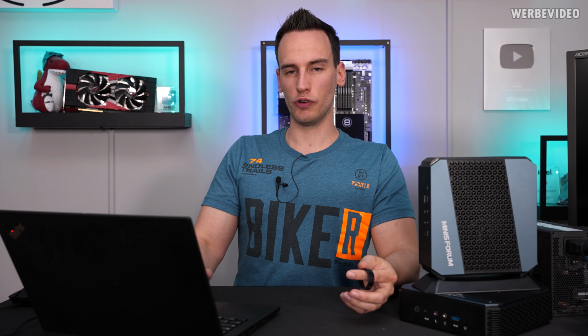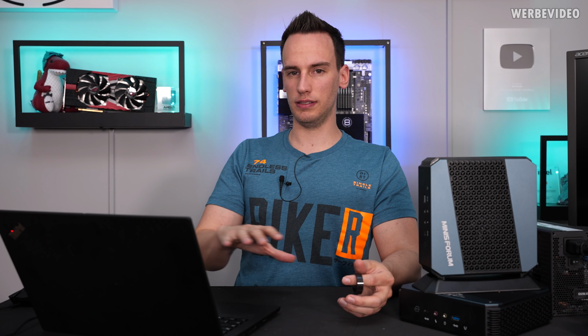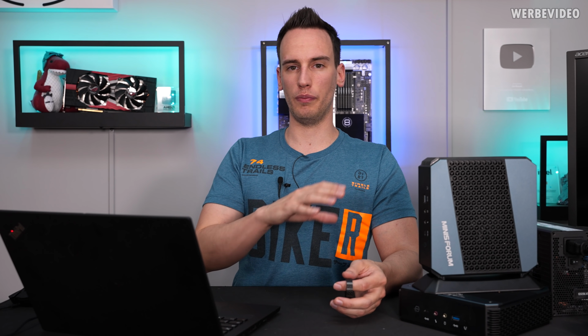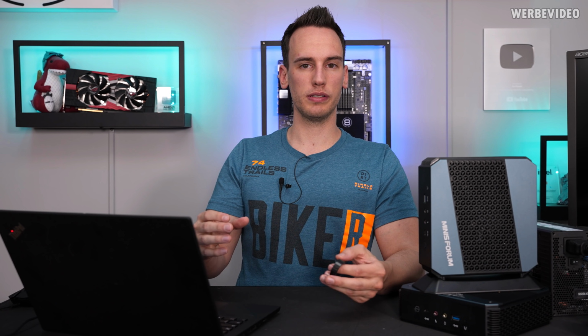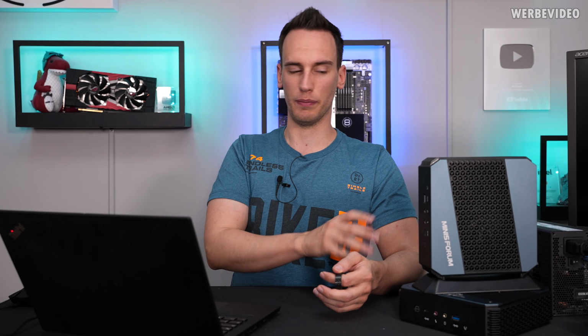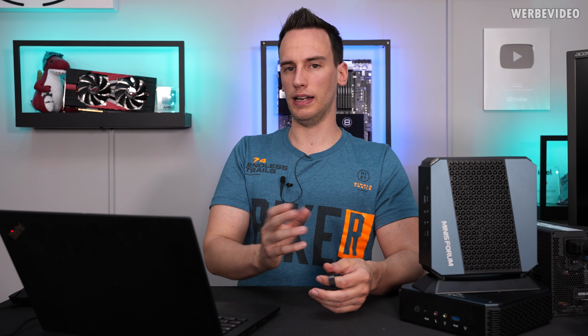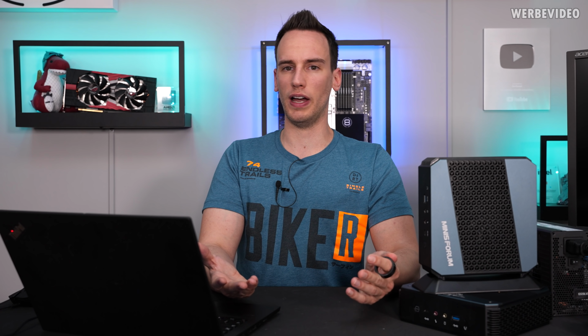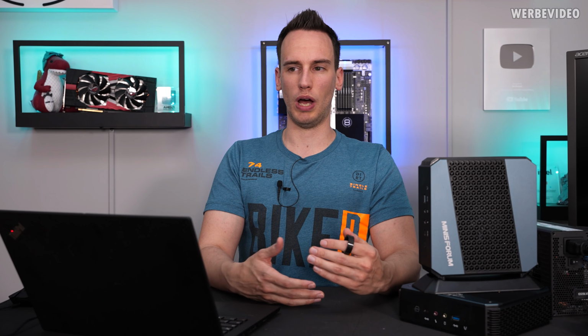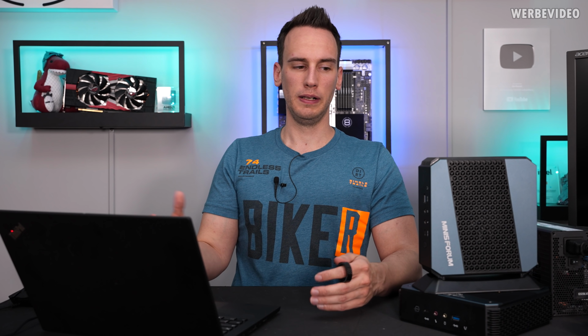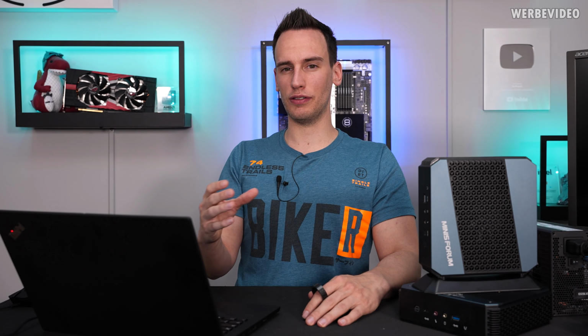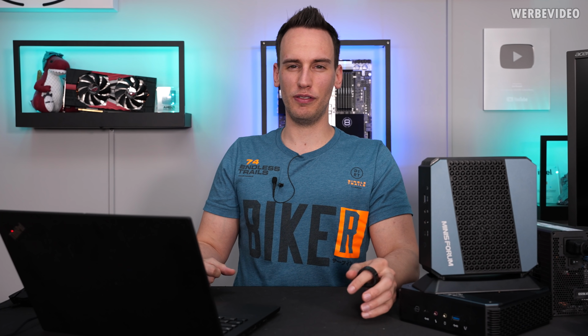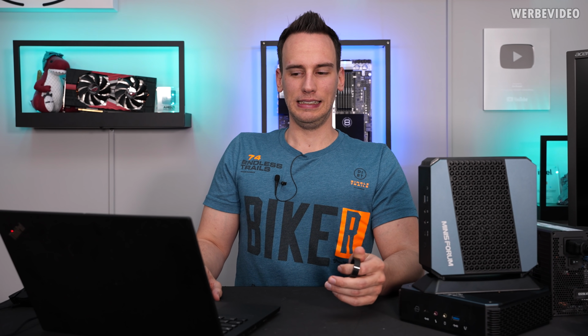3% carbon fiber. For sure, 3% carbon fiber will still impact the plastic from a mechanical standpoint. It will still be tougher, it will be stronger to be used as a case material. I'm not going to argue about that, it will definitely help. And it's also typical, if you do some research, you can find anything between 0.5% carbon fiber to up to 15% carbon fiber in injection molded plastics. But advertising that it's increasing the thermal conductivity if you add 3% carbon fiber, I don't think so.